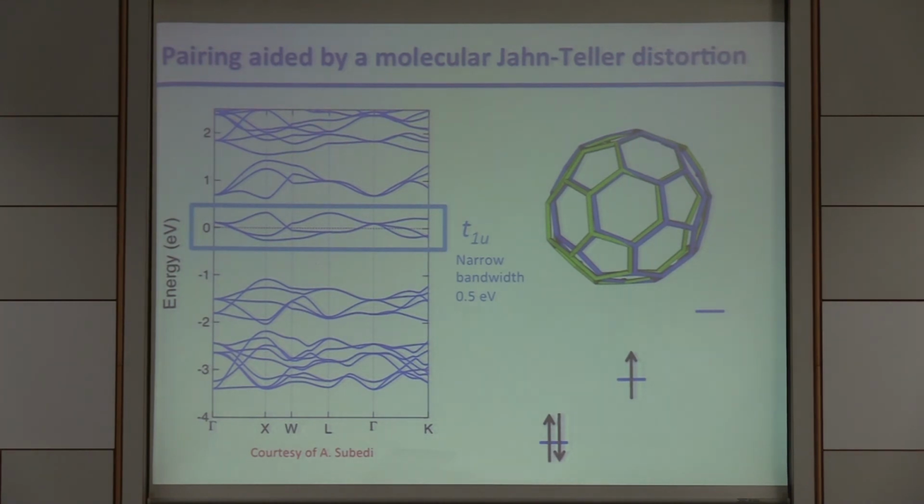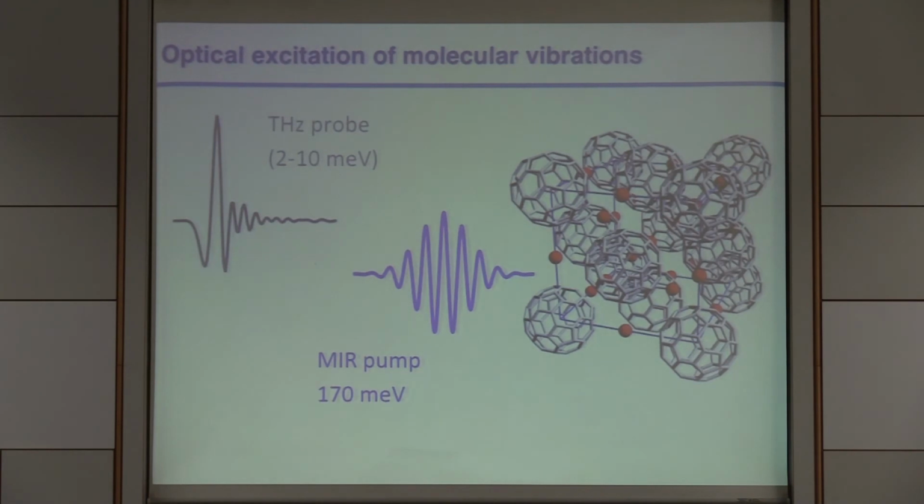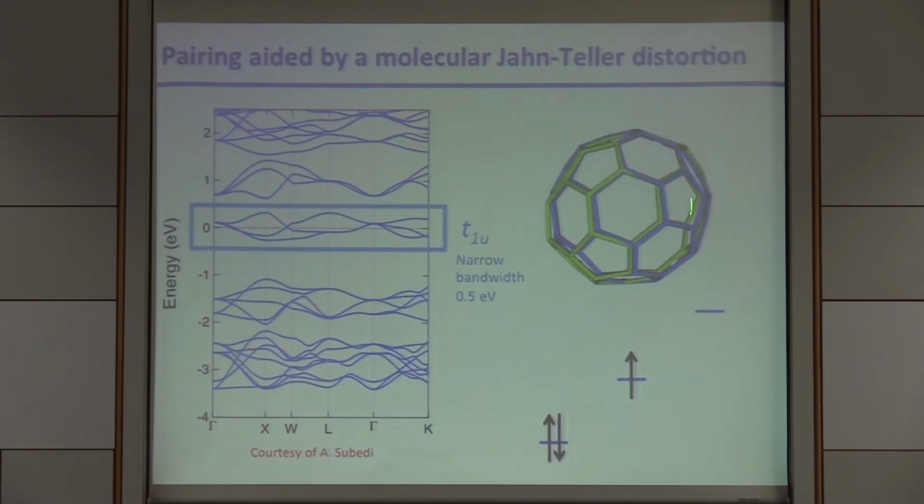So this low spin configuration of the C60 3- allows you to have a superconducting state. And so what I know is that this particular distortion, what I would like to do, and this is how we started, although it's unclear whether this is what's really going on, is that we were thinking, okay, we do the right shaking, and then on average, we will displace the system along this Jahn-Teller coordinate, which will stabilize these pairs. And we will make either a better superconductor or a polaronic insulator where nothing moves, where the pairs are really localized, or something between the two.